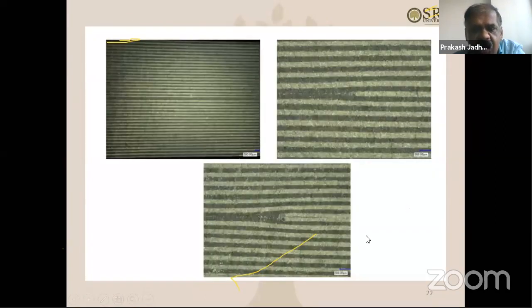If you look at this picture, the left side shows there are no ply drops. All the plies go continuously, so there is a constant thickness, no thickness variation. This is one example of a perfect composite. The second picture shows one ply getting dropped, and the third picture shows two plies getting dropped. So these are the simple designs that we have decided to try.